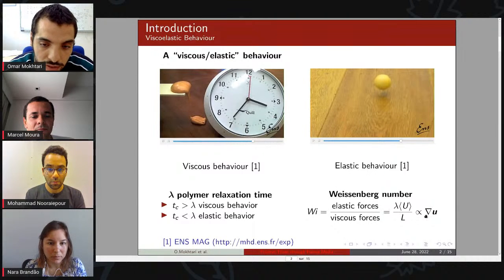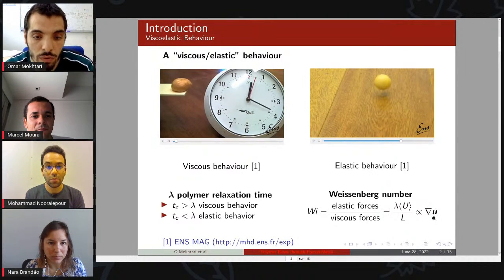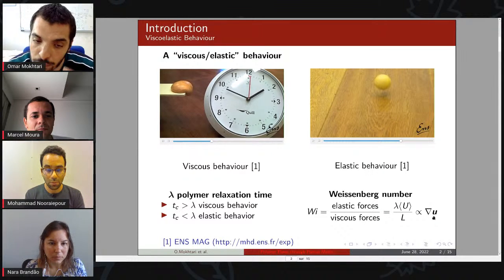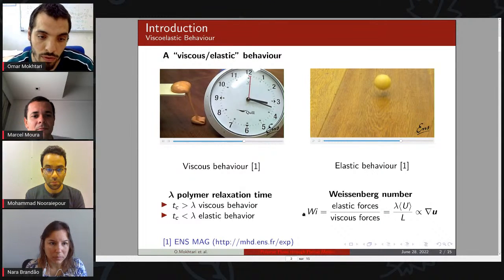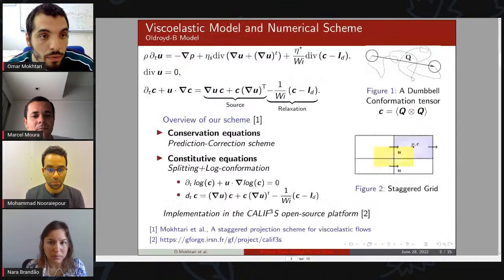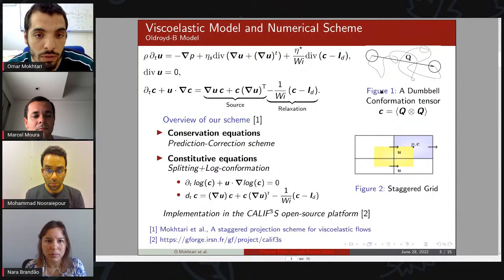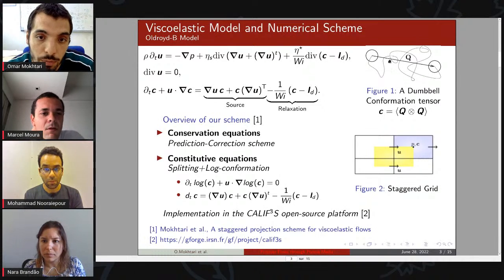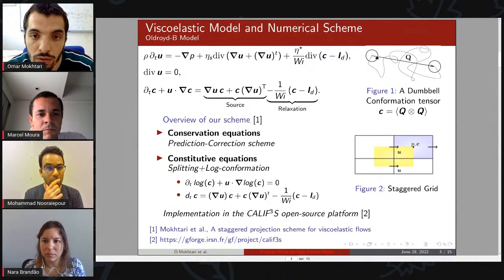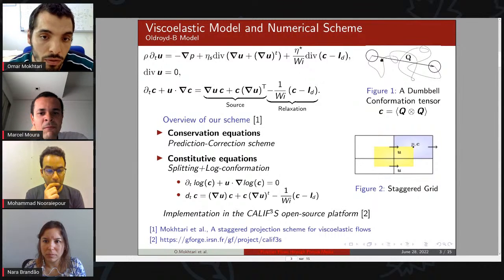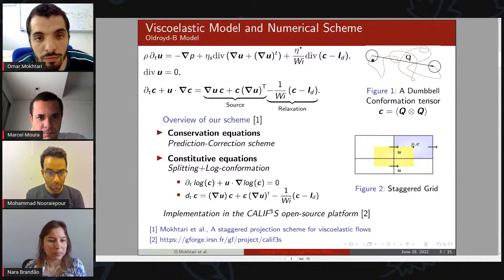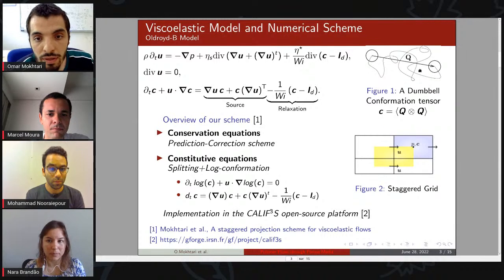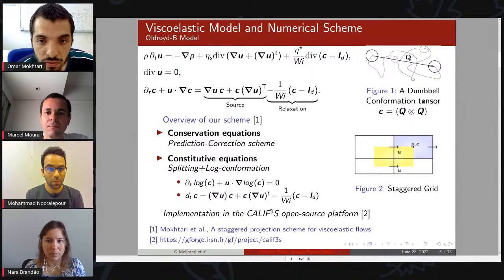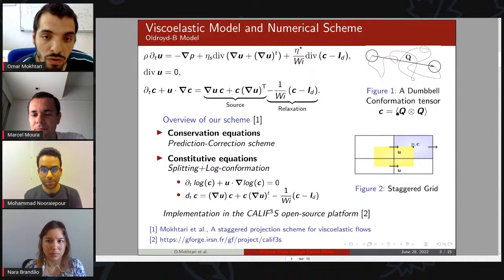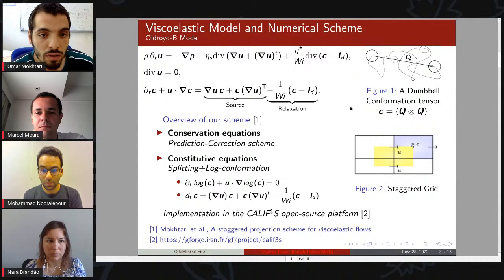And as we can see, it scales with a velocity gradient. So in porous media, where the Reynolds number is generally small, we can have high values of this number. To model this flow, we use a dumbbell model, where each polymer corresponds to a dumbbell with an entropic restoring force. If we define Q as the end-to-end vector, we can introduce the conformation tensor, which is the second order moment of Q, and this represents the conformation of the polymer in the flow.